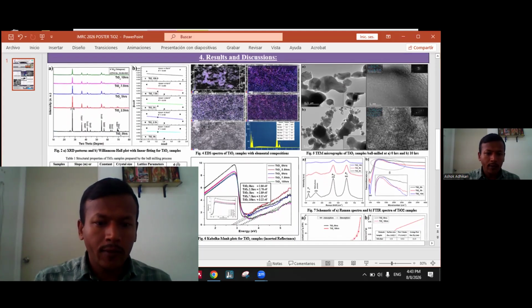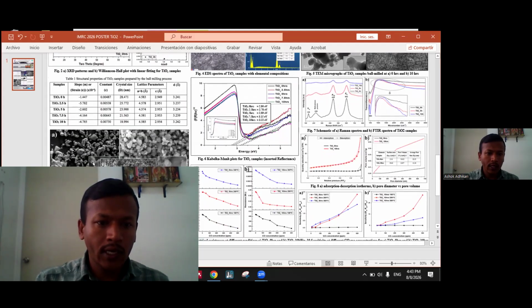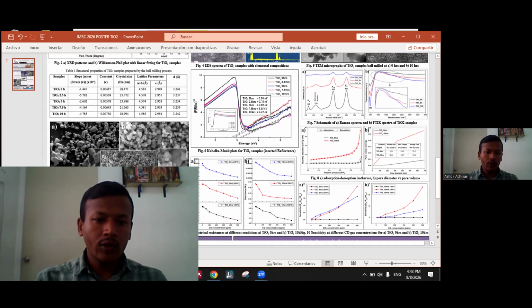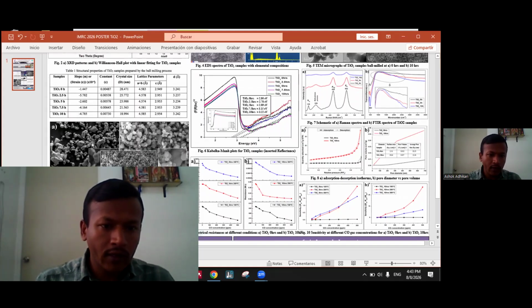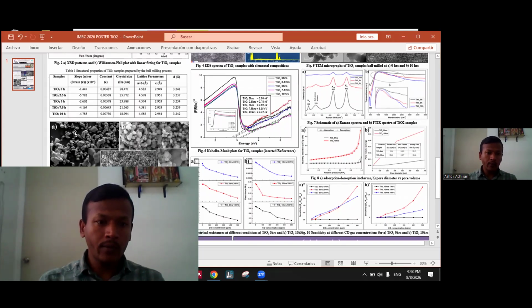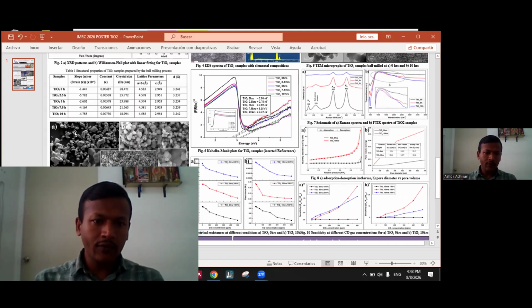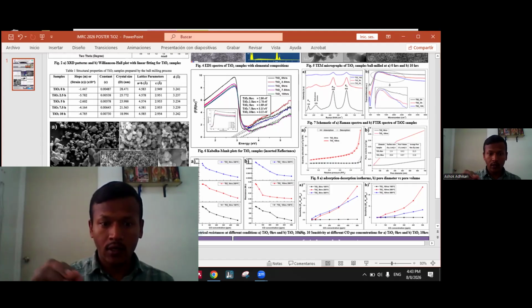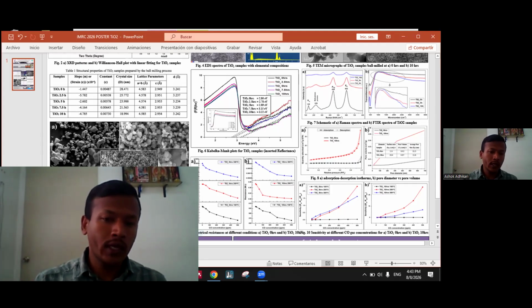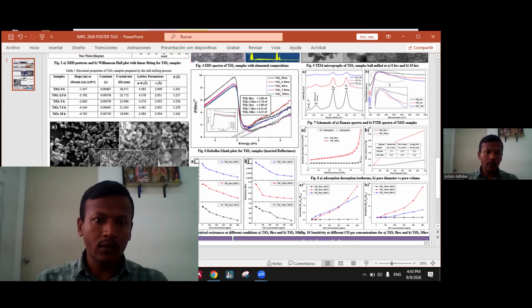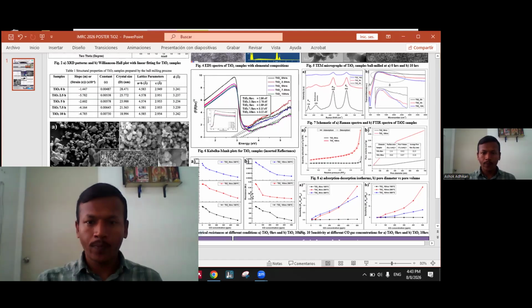After that, we have also checked the morphology. In the lower part, we have A, B, C, D, E, F. In figure 3, you can find initially without milling process, we have obtained geometrical precision, and even the grain sizes are more than one micrometer. After that, the grain size is reducing, and finally, in 10 hours, we have got homogeneous grains, and you can see around 100 nanometer. From these results, you can say that the presence of nanoparticles of TiO2 or nanograins is obtained.